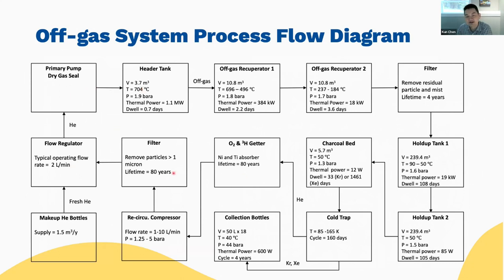So all of these calculations, this dwelling time, the thermal power, they're all based on an operating flow rate of 2 liters per minute. There's a possibility that we can increase or decrease it as needed, but in normal operation, the flow rate will be kept at 2 liters per minute, which is adequate for the operation of the system. There's also a makeup helium bottle here. It supplies fresh helium, which is obviously necessary, because when we start the system, we need the helium from somewhere. And also there are going to be some leaks, and then you have to supply additional helium. There are also other functions like using helium to flush the system.